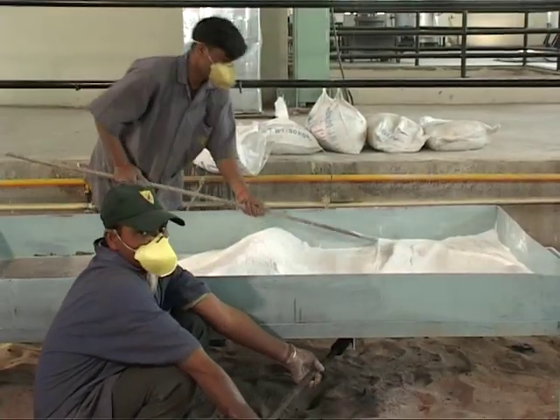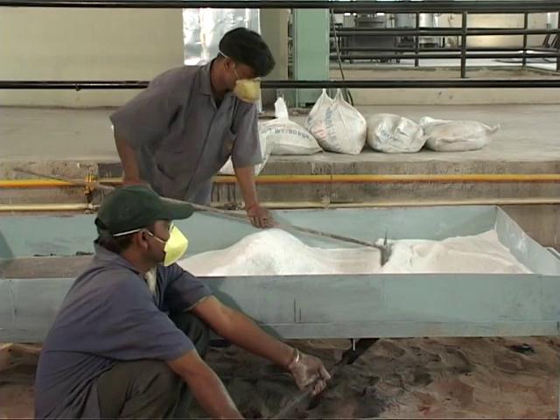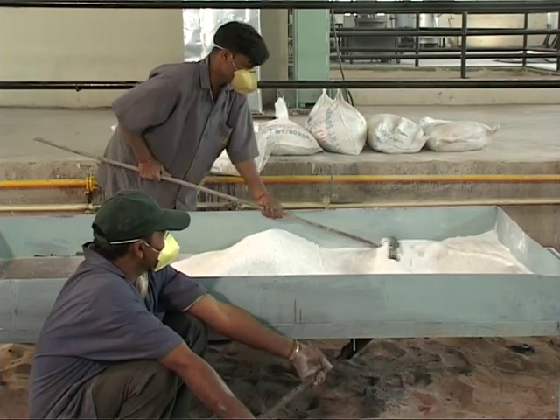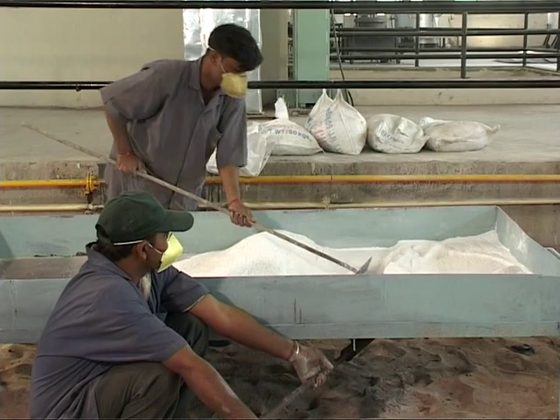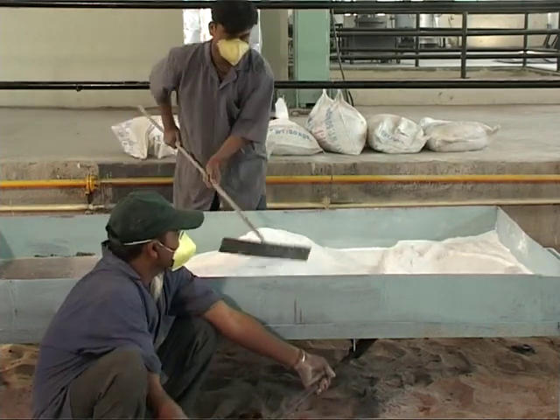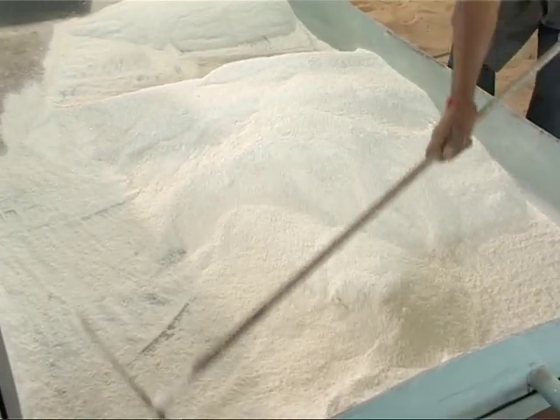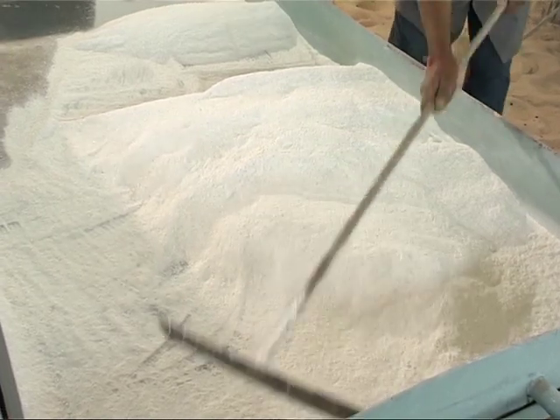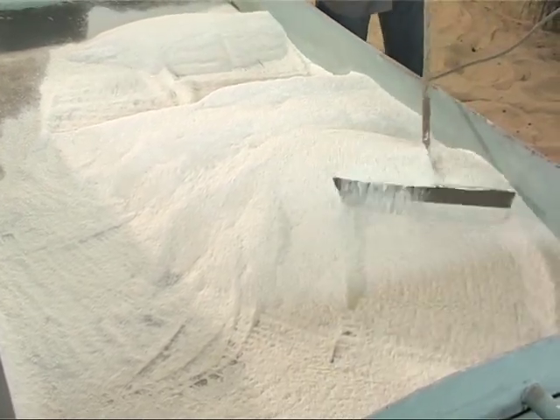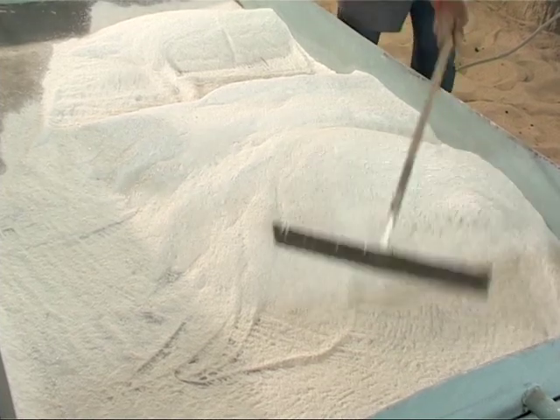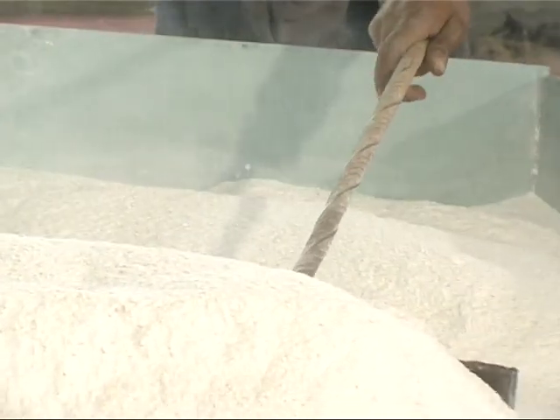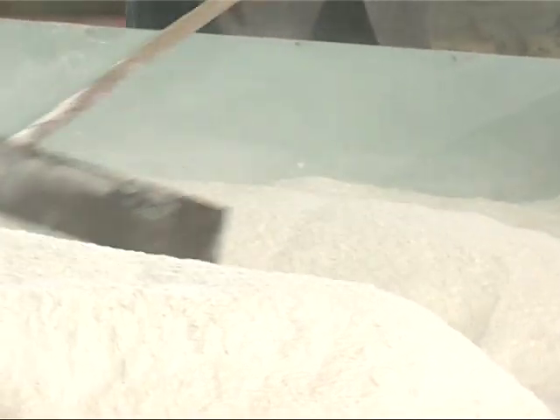Stir the ramming mass frequently while heating. If it is noticeably damp and the powder sticks to the palm after holding a fistful, then it will require a couple of hours of drying out. If drying is insufficient, the steam formed on sintering will open up cracks, forming passages in the lining. Then transfer it to a cooling tray before mixing, in that same tray or in a mixer. Cool the ramming mass until it is so cool that you can hold it in your palm to the count of 10.